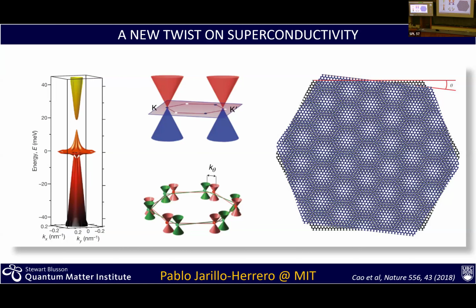In an ideal system, this would be something that I would put a lot of trust in in terms of predicting ability. The problem is when you make devices, all kinds of effects come in, including bubbles that form here. The angle is not exactly homogeneous everywhere, so those details really play a big role. If the system was ideal and didn't have all these imperfections and additional local interactions, I would say that given that graphene is very well described by density functional theory, I would put a very strong level of trust in here. At this stage, I think deviations from that are really coming from the challenge of making the devices.